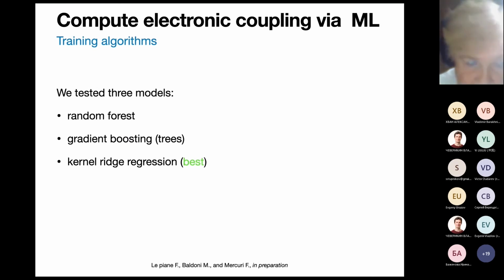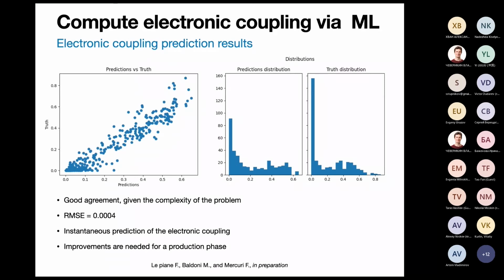And finally, these are the preliminary results that we got very recently. As you can see on the left, there is good agreement given the complexity of the system, this problem, which is very demanding from a structural point of view. So we have a relatively small error. And this allows us to have instantaneous prediction of the electronic coupling, so we can increase our overall throughput in the material discovery activities. And you can see also that the distributions of the prediction and the truth are very similar, which is very encouraging for us.